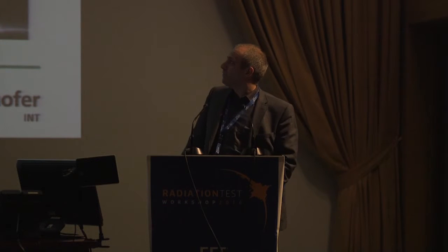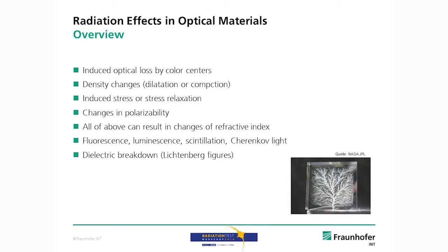Then there are active ones, where light is induced by different effects: fluorescence, luminescence, scintillation in some materials, or, if you have particles faster than light in the medium, which is easily done for electrons, then you have Cherenkov light, which is a little bit like an ultrasonic boom you have mechanically for an airplane. The particles induce an optical shock front.